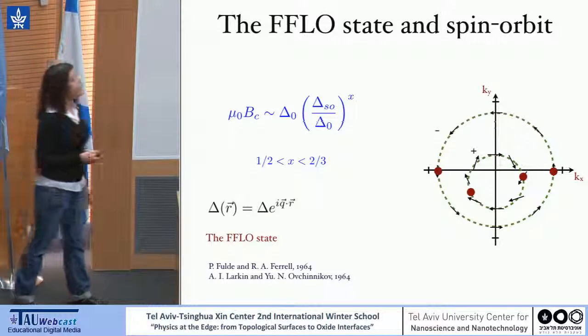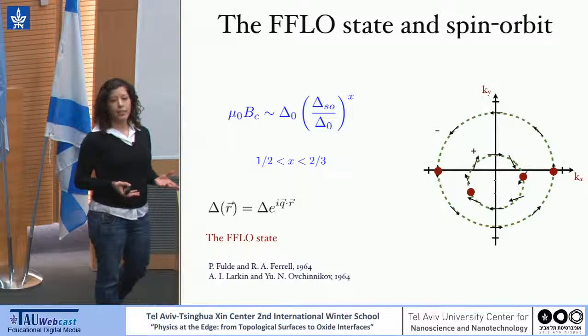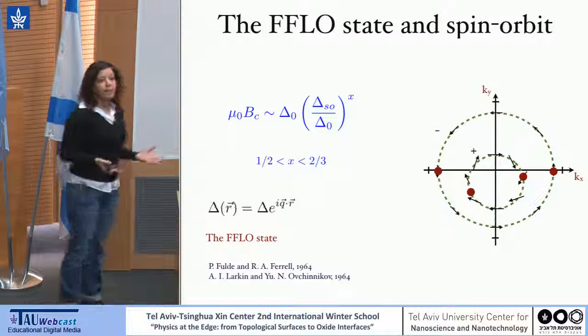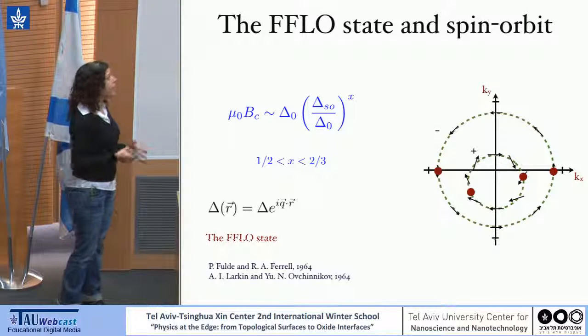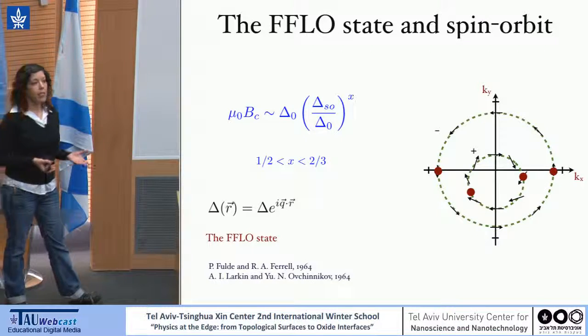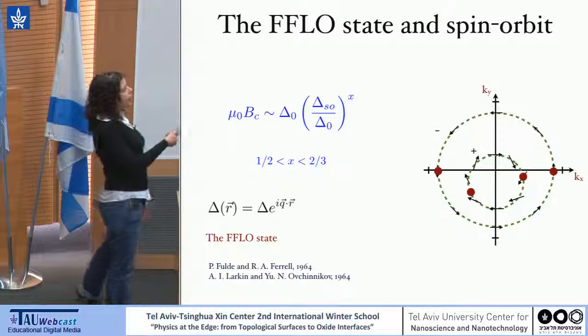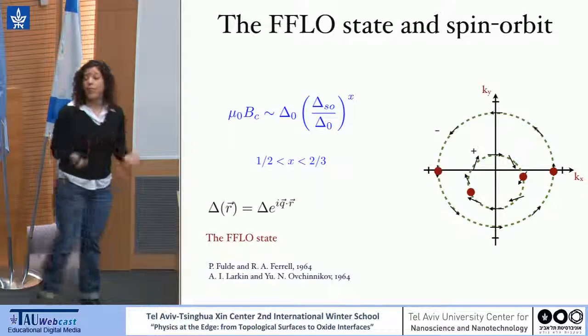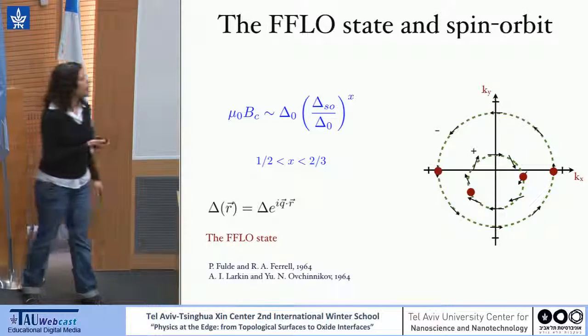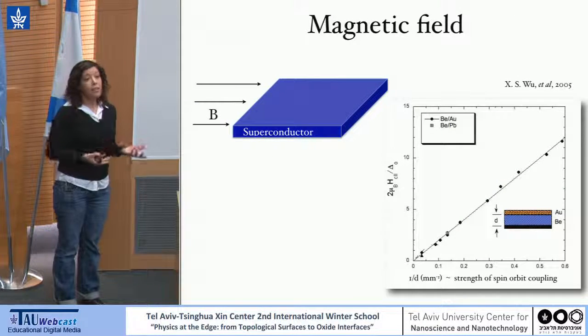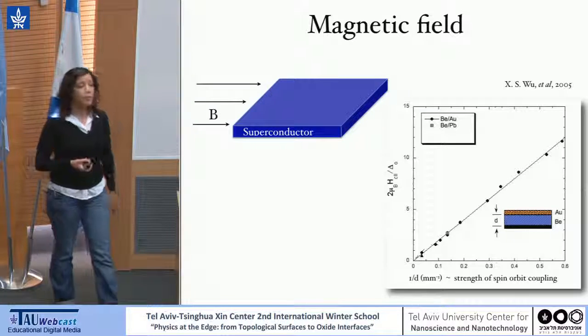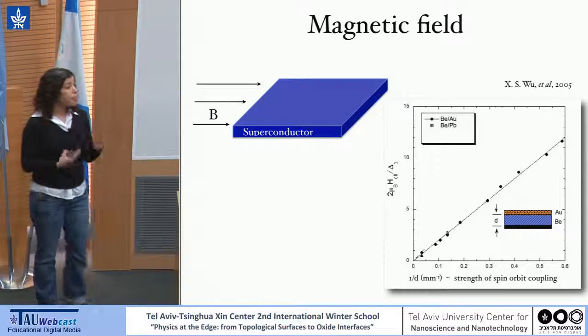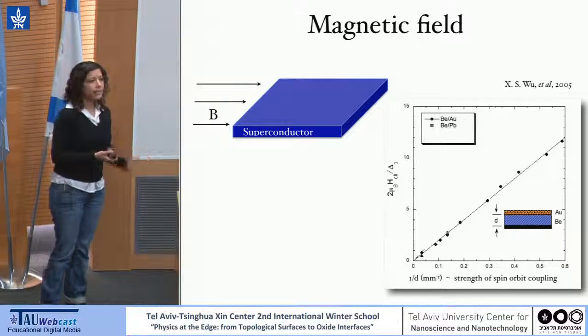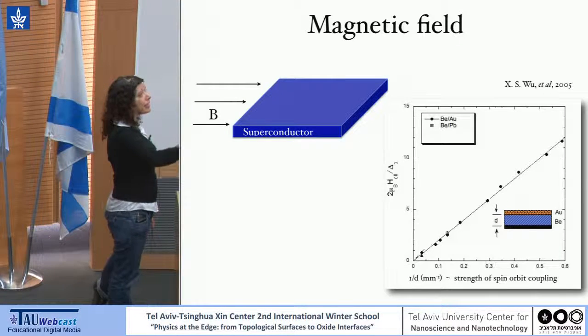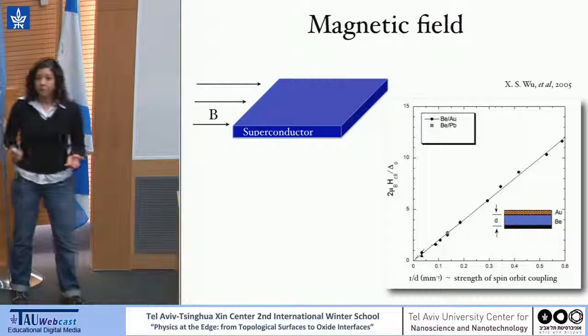And what we are getting here is a unique superconducting state, which is many times referred to as the FFLO, the Fulde-Ferrell-Larkin-Ovchinnikov state, where the order parameter actually has a finite phase in it. Now, we can understand from this kind of explanation how, in the presence of spin-orbit coupling, we can get this large enhancement of the critical field.